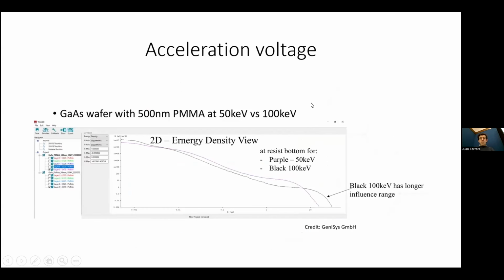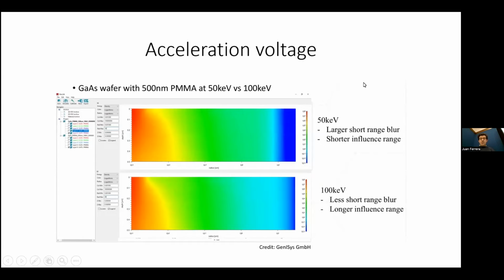And this shows the difference in acceleration voltage. So if you use a 50 kilo electron volt beam to expose 500 nanometers of PMMA, you see that here you have a fairly large amount of forward scatter, but a smaller amount of back scatter compared to 100 kilo electron volts, where the situation sort of reverses. You have less forward scatter, but you have larger back scatter range.